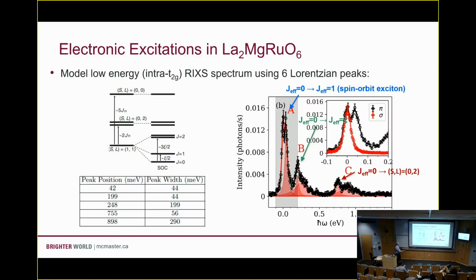So in the strong coupling regime, these spacings, J equals 0 to J equals 1, J equals 0 to J equals 2, are just related to the size of the spin orbit coupling. Okay? This goes like lambda over 2, this goes like 3 lambda over 2. This spacing here is just related to the Hund's coupling. So we're getting to directly pull out these single ion parameters.